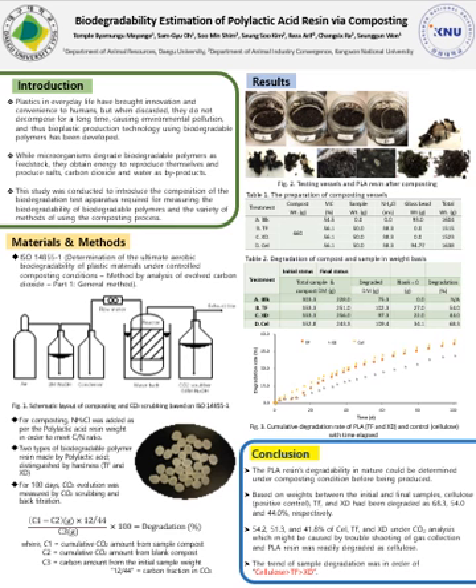and the important information to get here is the degradation percentage, which was 68.3 in cellulose, followed by TF 54, and finally 44 for XD. Then the last figure here shows the cumulative degradation rate of polylactic acid, the two samples and the control, with time elapsed.